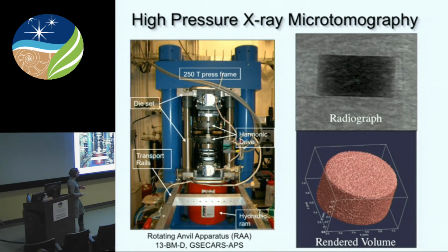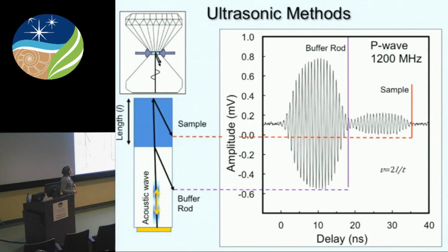This is actually a sample of silica. That's a little disk that we use to measure volume. So this is volume. How do we get density? Well, we start off by measuring the volume at 1 atmosphere inside the press, and then if we take incremental steps as we increase both pressure and temperature, we can measure the density as a function of these variables, getting a compression curve. Okay, to get at things like velocity, I use ultrasonic methods.